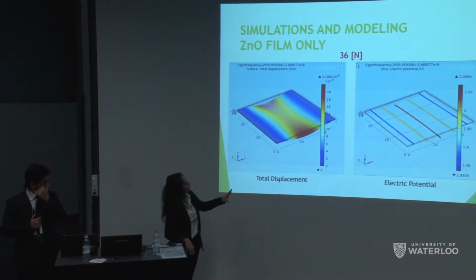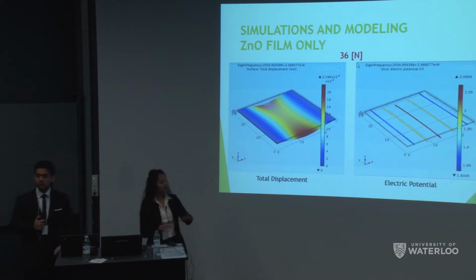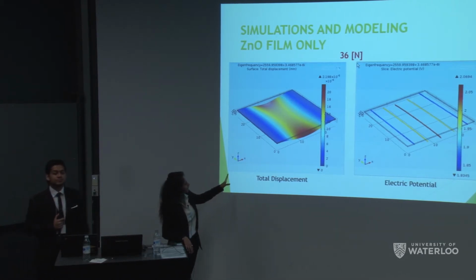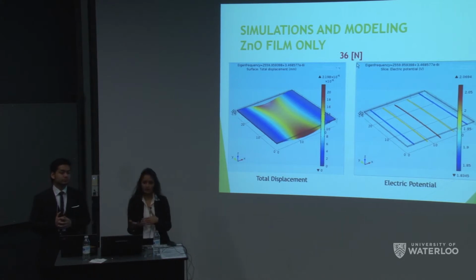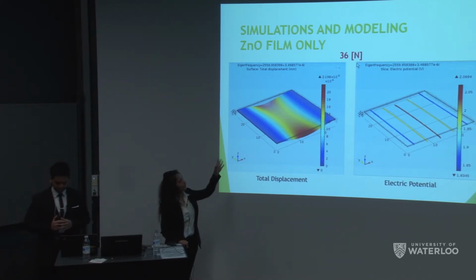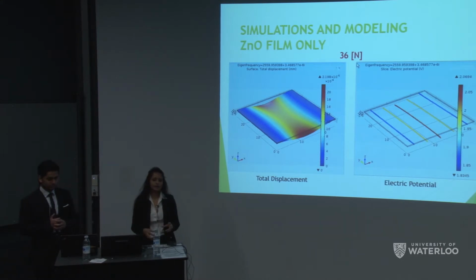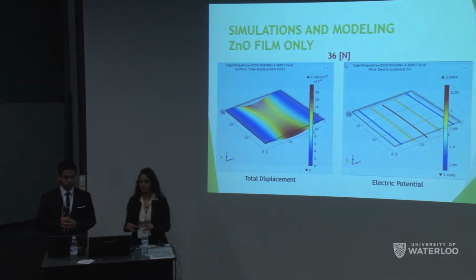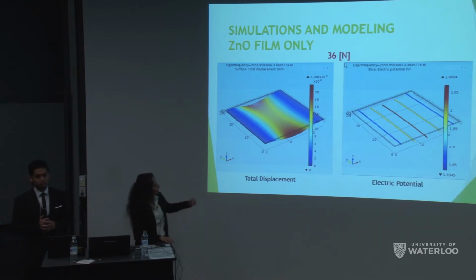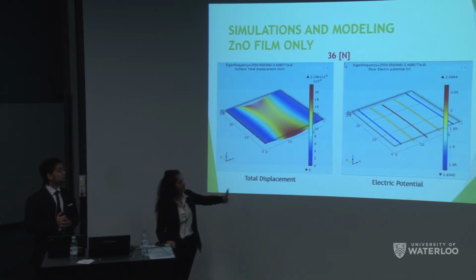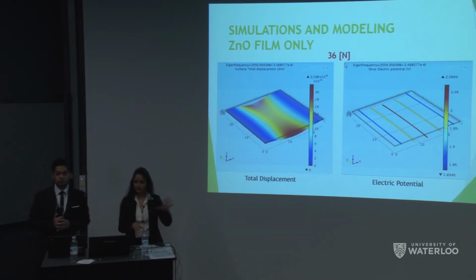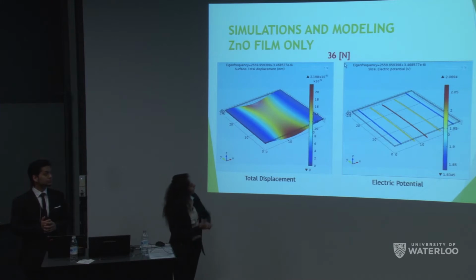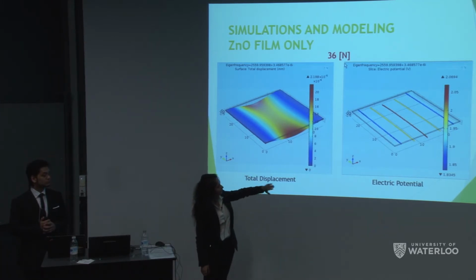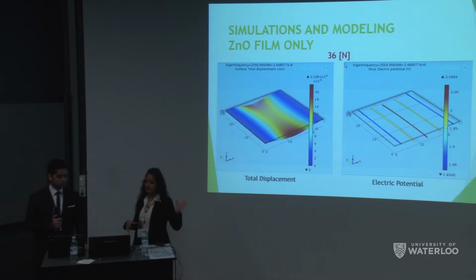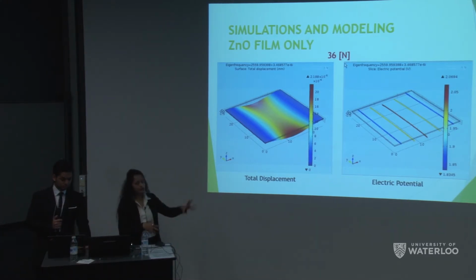So the plots that you see here are just zinc oxide films, like bulk films. The graph on the left shows how the displacement profile would look for the zinc oxide film when it experiences a force of approximately 36 Newton, which is what we estimated is the amount of force that an average male's heel strike generates. And the plot on the right shows what kind of potential plot it would generate on the entire zinc oxide film. We can see from the plot that the simulation tells us that with this kind of structure, we can almost achieve a little over 2 volts, which is what we started off as our benchmark.